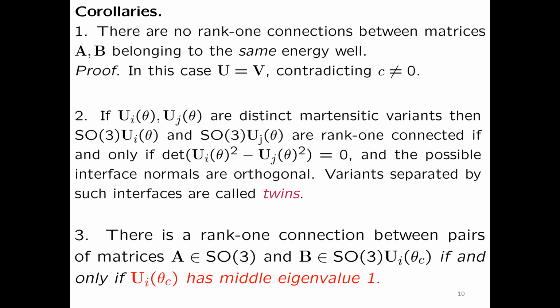Are you trying to justify why in these microscopic images we see various vertical lines, vertical planes, of course, in three dimensions? So the fact that there's this connection implies that I have these different matrices acting on the cubical lattice, and they're connected by the same thing on these vertical planes. It's leading to calculations of what interfaces are possible between different zones.